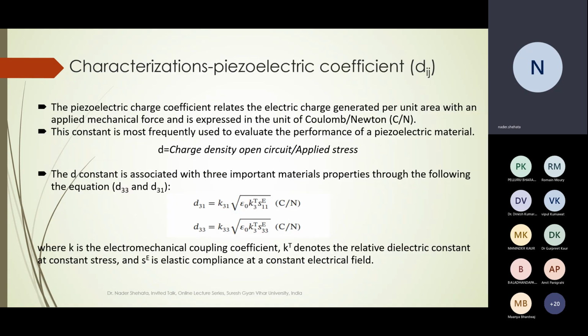Other parameters that are very important to measure the piezoelectricity of the material are the D coefficient and the G coefficient. The D coefficient simply means the formed charge compared to the applied stress or applied force, and its main unit is Coulomb per Newton. But for 1 Newton, we are expecting relatively small charges, so most likely it would be in the range of picocoulomb per Newton for most PVDF nanostructures or nanofibers. Here, this D is a tensor, or it has a matrix related to the direction of the applied force and the generated voltage or generated charge.